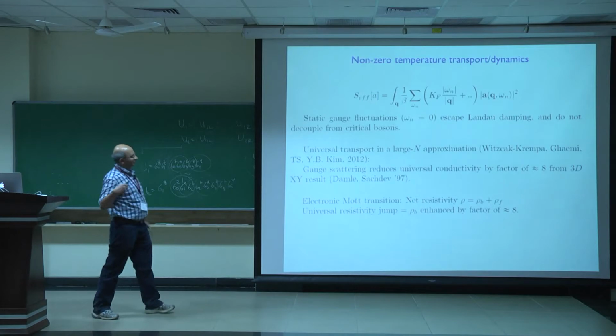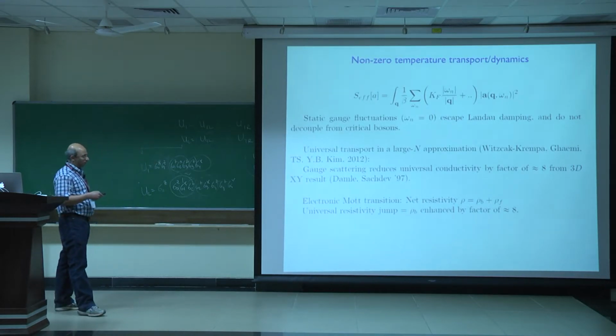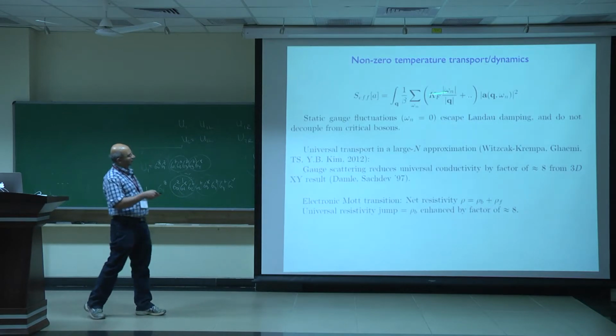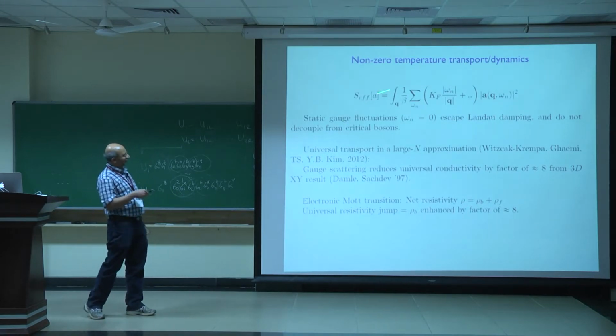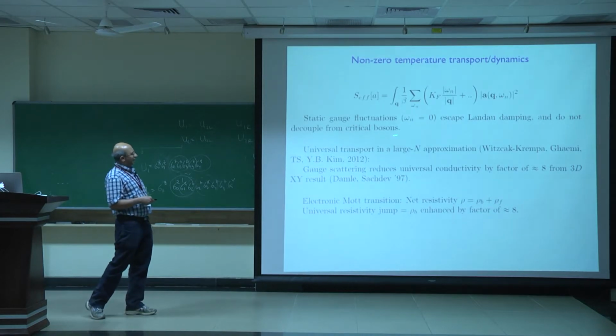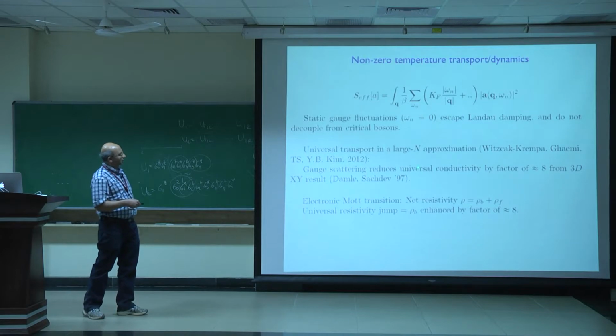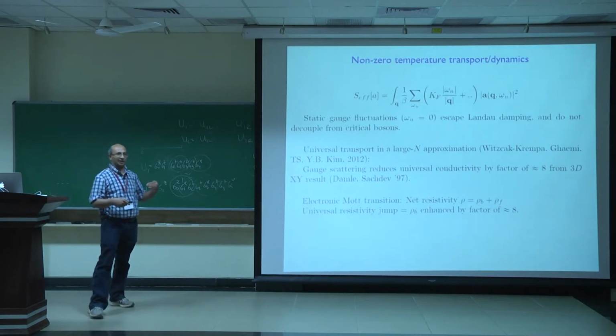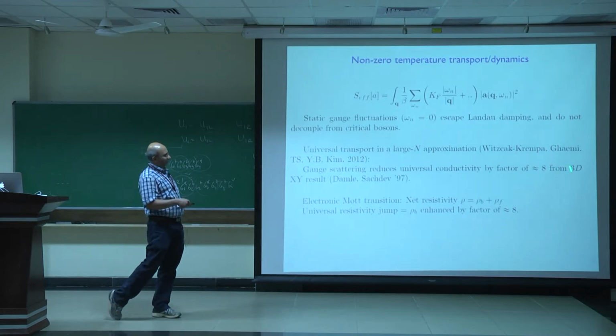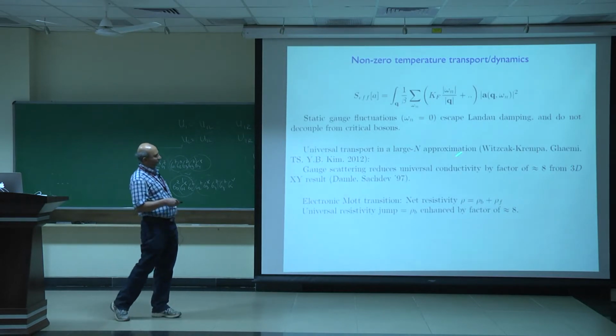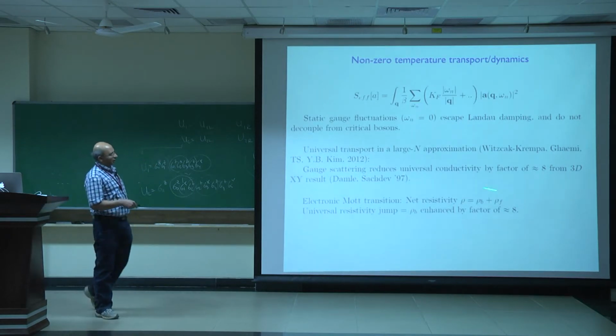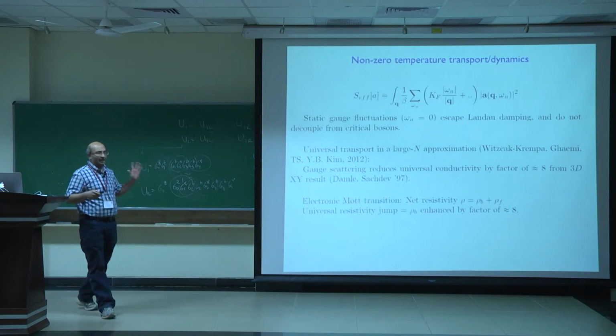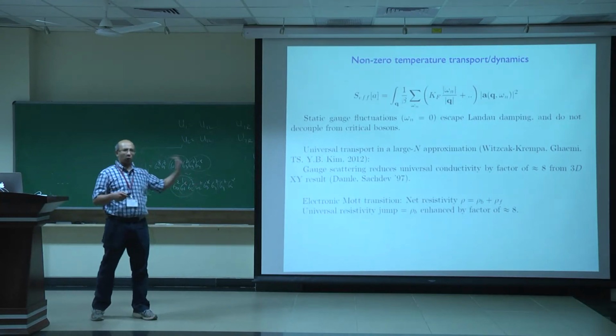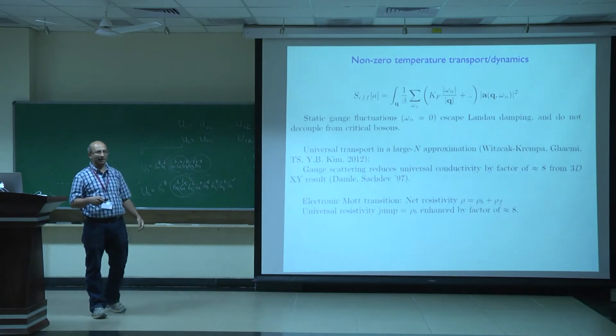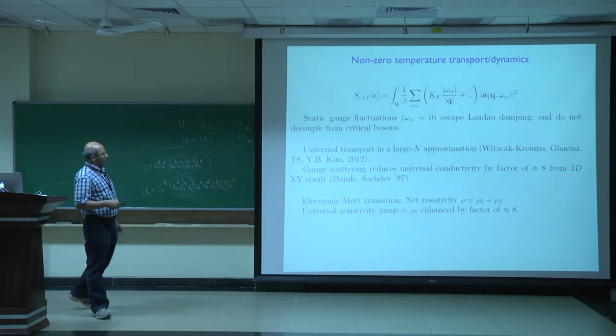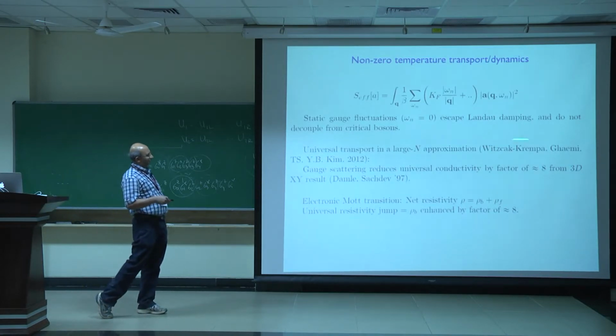But here, we can build on the theoretical technology that Kedar and Subir developed and include this extra scattering mechanism and calculate the universal conductivity while including this. And it turns out that what it does is to reduce, not surprisingly, the universal conductivity because of extra scattering. And at least in the large N approximation, it reduces it by about a factor of 8. I don't know if the number 8 should be trusted in general, but the qualitative phenomenon is that there's a reduction of the universal conductivity compared to the problem without the gauge field.